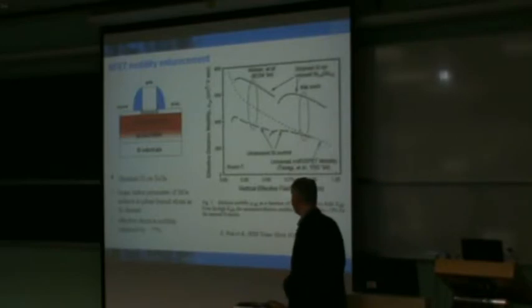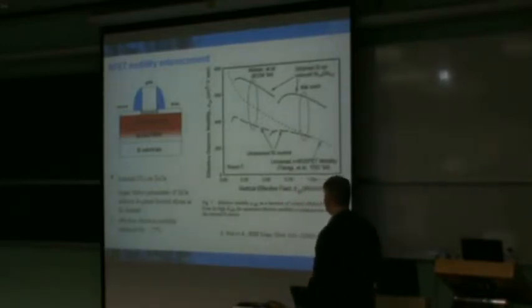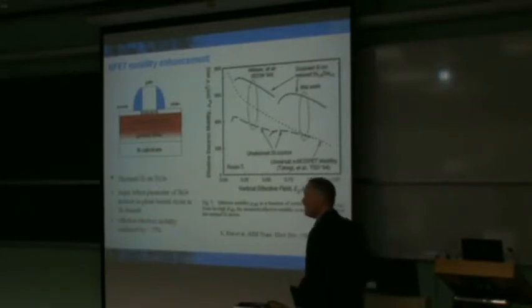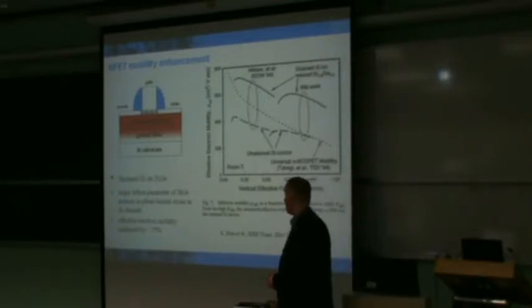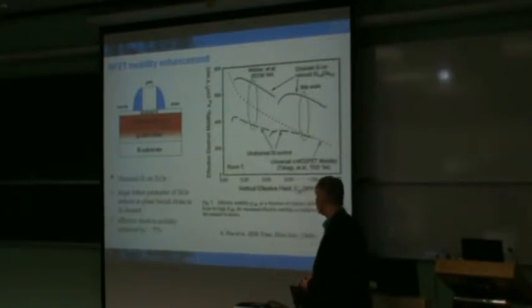In this case, clearly you can see that this is a biaxial case, which just means that both in-plane directions show this larger lattice parameter. And so therefore you get this in-plane biaxial strain within the silicon channel. What does that do? So if you look at some of the curves then, in terms of the effective electron mobility, you can get an enhancement. In this case, it was demonstrated close to 75%. And it is theorized that this can easily go up to 2x or so in terms of NFET mobility. So that's quite a large knob to make.